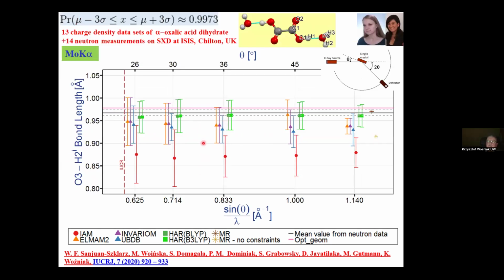In the case of bonds to hydrogen atoms, we see clear differences. I was mentioning the standardization normalization procedure. In this procedure, people were extending bonds to hydrogen atoms from those obtained using the independent atom model to the neutron ones, to these ones. Whereas when we are using Hirshfeld atom refinement, we are already getting neutron type bond lengths to hydrogen atoms.